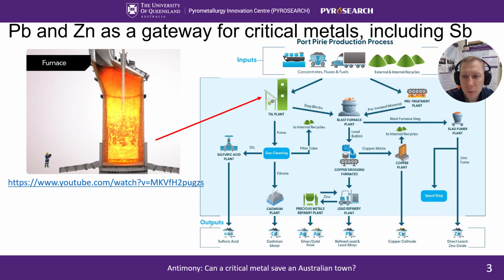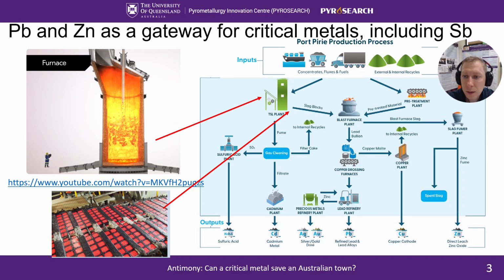The gas is cleaned from the dust, which is recycled back, and the clean gas is converted to sulfuric acid. I must mention that sulfuric acid is essential for most hydrometallurgical leaching types of operations, as well as production of fertilizers. The gas cleaning also produces cadmium as a byproduct. Slag is then cast in molds to create high-strength blocks which are suitable for further processing in the lead blast furnace. The leaching residues from zinc operations in Hobart and other materials with high moisture content are baked in a sintering machine to make them suitable for the blast furnace.